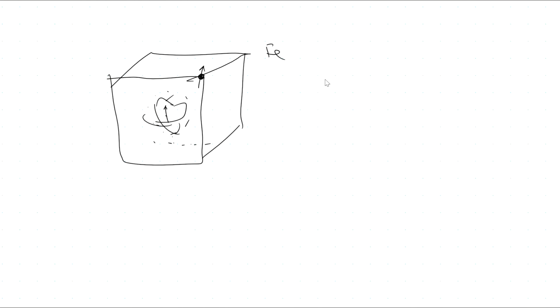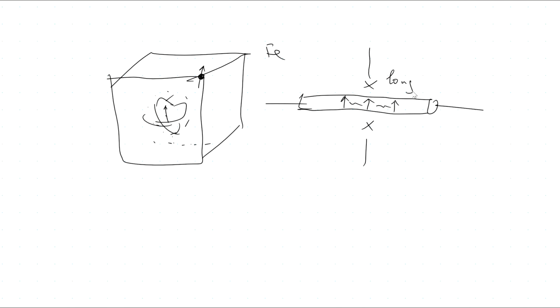And in case of the cube, it's less obvious, but if you go back to our wire, a magnetic moment in the wire here interacts with magnetic moments to the left and to the right. There are interactions there. At the same time, there is no magnetic moment here and no magnetic moment there. Therefore, there is less interaction along this axis, more interaction along that axis. So it is long in this direction and narrow in that direction.